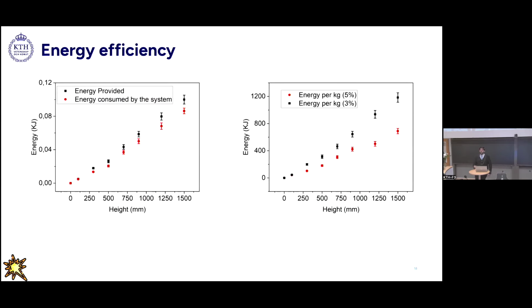So if we want to establish this as a process, then we wanted to see how the losses look in our system. You can see the energy provided to the system and the energy which is going towards the actual production of shock wave. There's a lot of difference. The major difference comes from the frictional losses that the weight carries while dropping on top of a chamber, and also some of the instrumentation that we have used, which is not really relevant to the shockwave production, but we need it for the characterization of shockwaves.